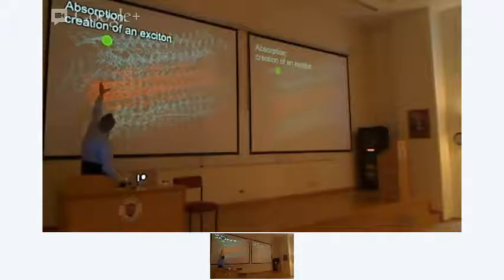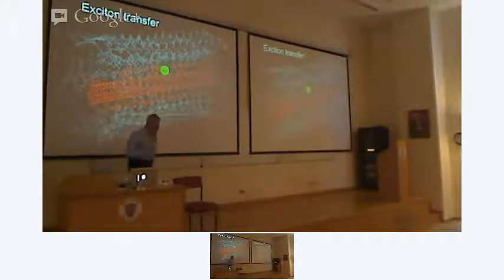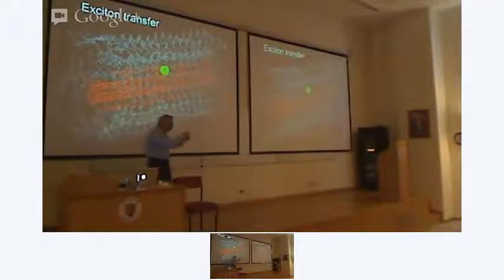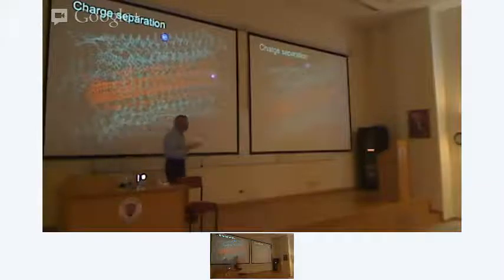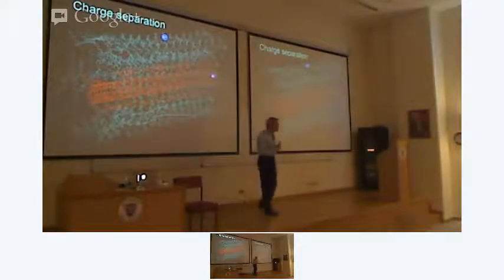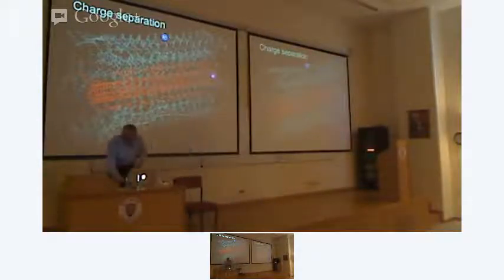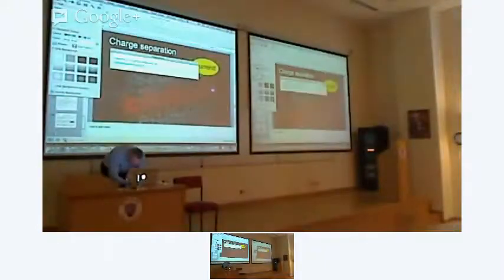One of these molecules in the polymer has been excited. This exciton starts to move around between those molecules using the processes I just described to you, downhill. It gets into this interfacial region, where the exciton states and the so-called charge transfer states become similar in energy, and charge transfer takes place, and you get electrons moving along the conductor and holes moving around in the hole conductor. The polymer actually is a good hole conductor, it turns out, in this particular case. And so this is a piece of material that in principle can function like this, and give rise to current. Okay, I think I'm going to stop on that one.